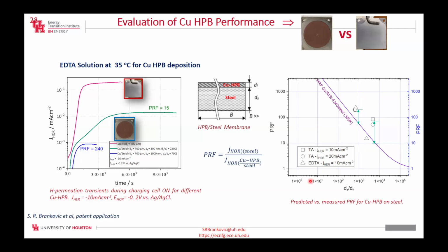In fact, the way that we are synthesizing our copper, it's actually better than pure copper because, through the synthesis process, we introduce certain impurities which act as hydrogen traps, which additionally slow down the permeation process, but also increase ductility of the copper and improve the grain boundary quality. Therefore, unlike in pure copper, where the grain boundaries represent a fast diffusion path for hydrogen, in our case our grain boundaries are saturated with those hydrogen traps, and hydrogen does not permeate through the grain boundaries of copper, which is an interesting thing.